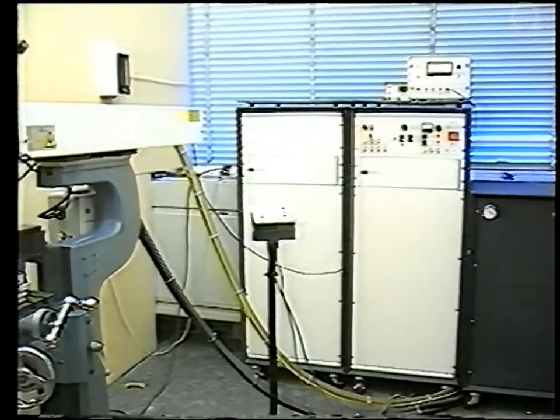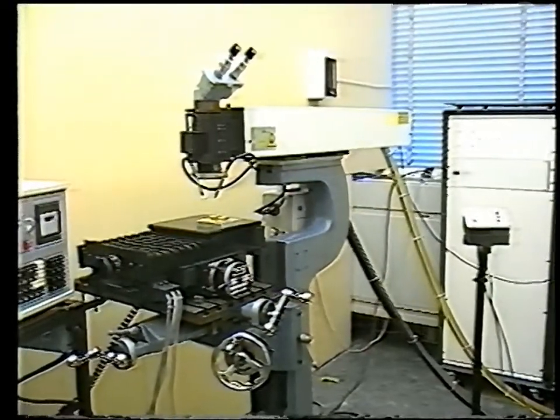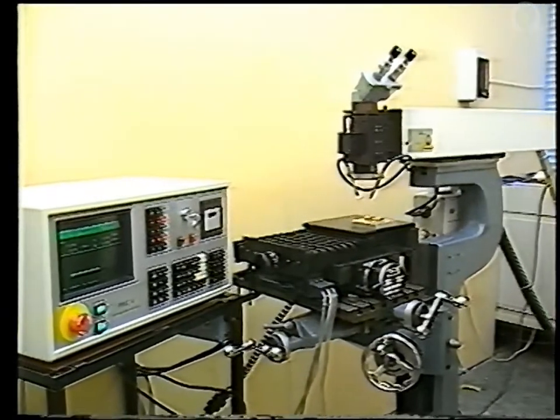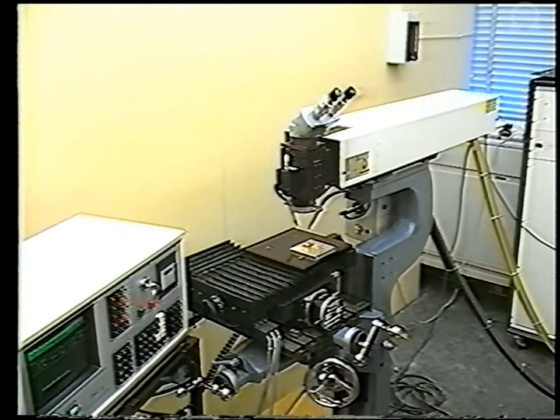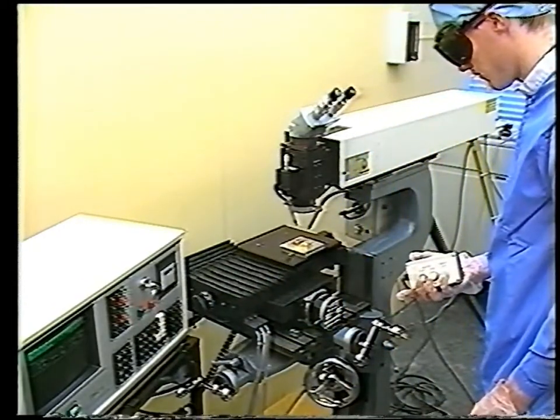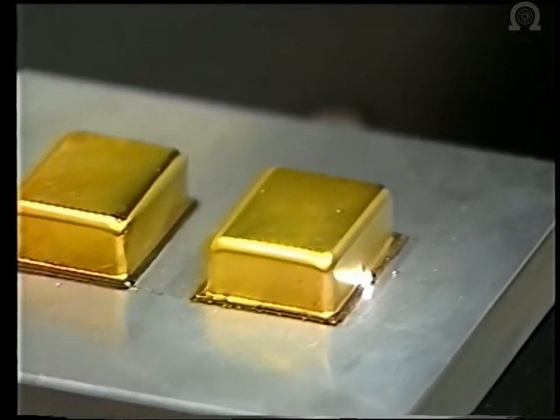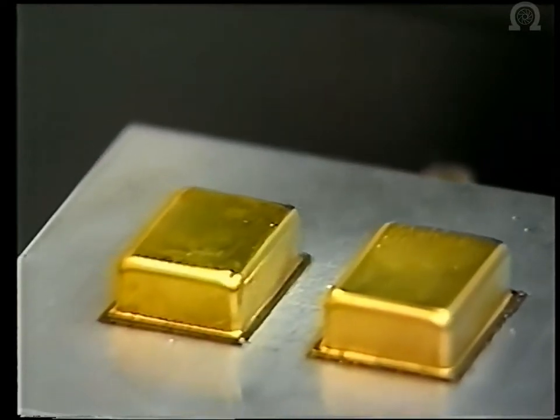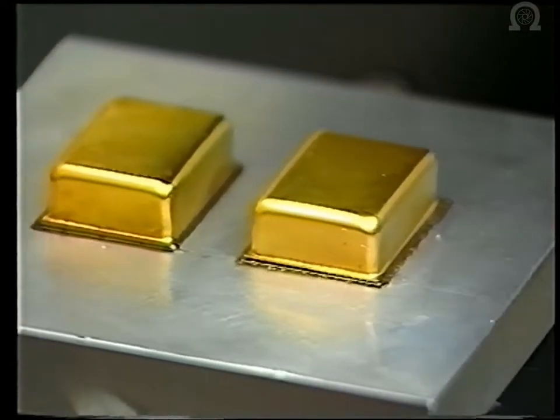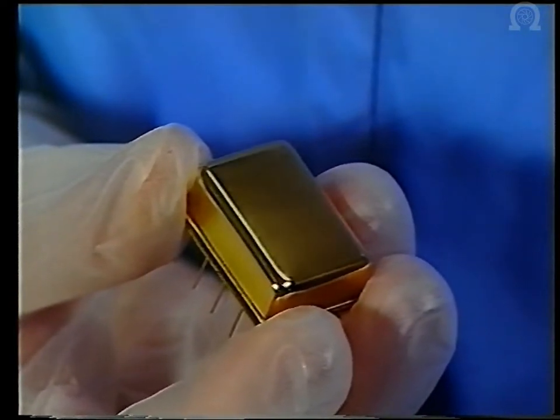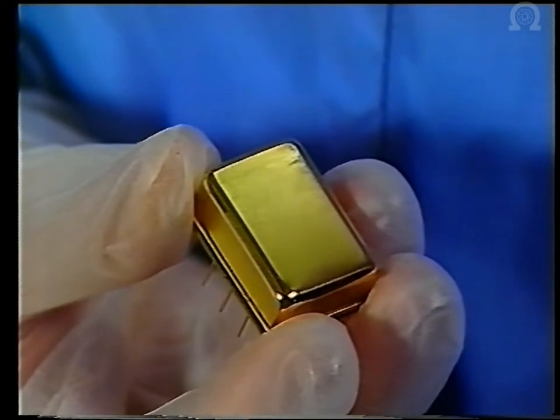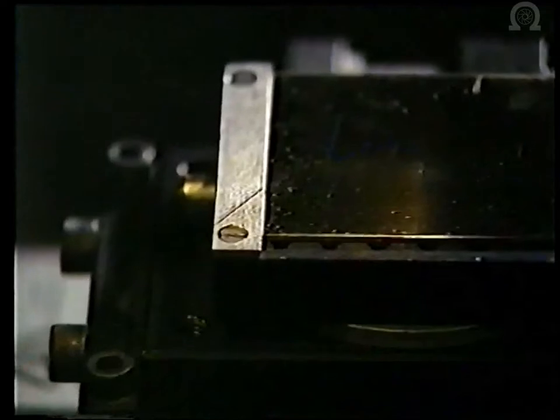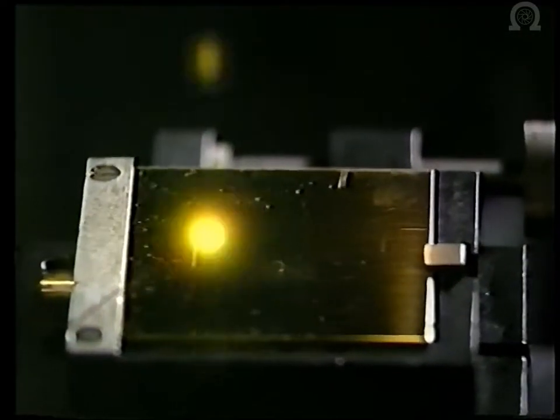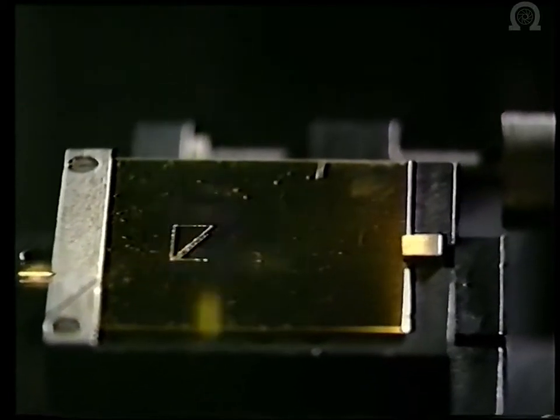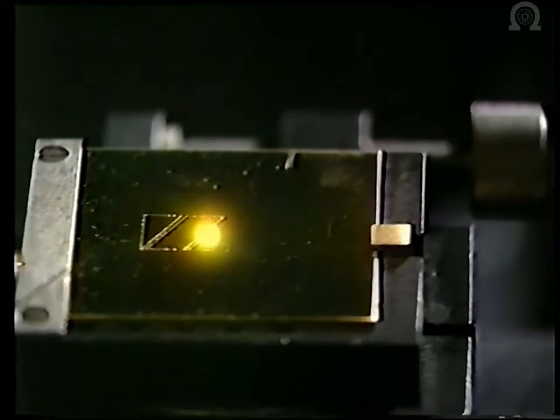An alternative sealing technique is laser fusion welding. This 300-watt neodymium YAG laser operates at a wavelength of 1.06 micrometers and is being used here for welding gold-plated Kovar packages. The XY table is microprocessor controlled and enables welding to be carried out at a constant speed even around corners. Like seam sealing, the heat input during welding is low and the circuitry within the package is not exposed to temperatures in excess of 125 degrees Celsius during welding. The laser process is, however, more versatile than resistance seam sealing, since dedicated machines are not necessary and lasers can easily be used for other welding and machining operations, such as scribing.